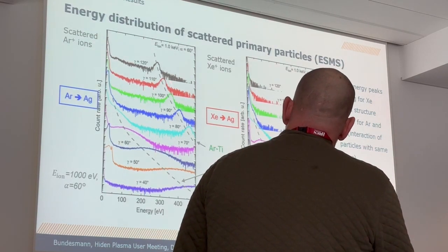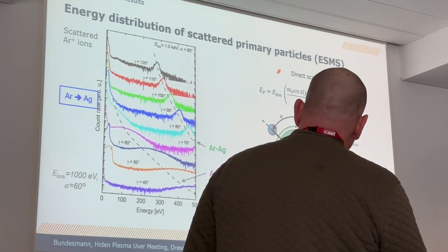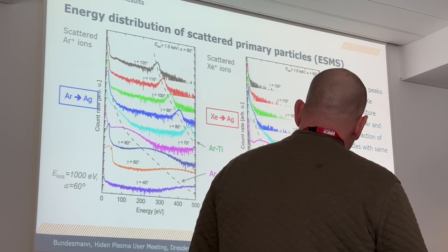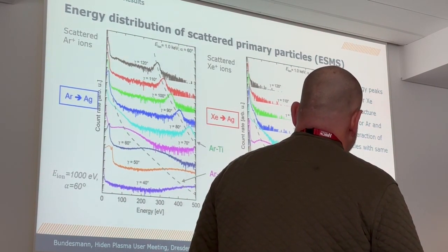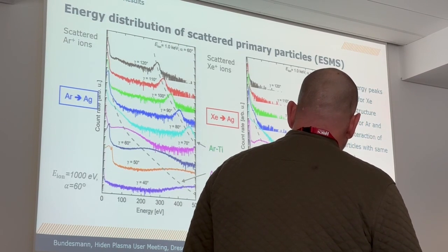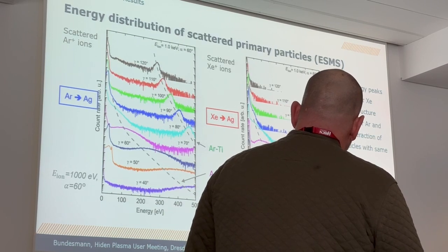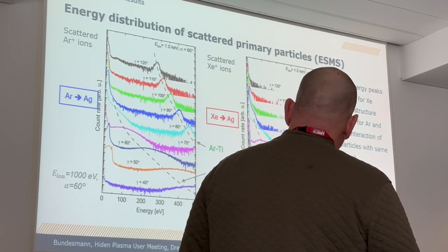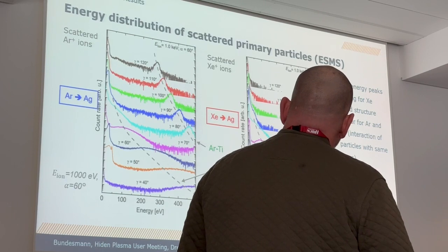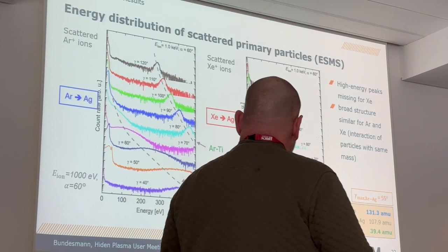So here we have what we already explained. We have a larger scattering angle range than in this case. So this peak is missing. It should appear at an angle of less than 55 degrees. So at 50 degrees, we would expect the peak at about 250 electron volts. At gamma 40 degrees, it would be somewhere around 500. It's not here. Perhaps it's subsumed by this broad structure. I'm not sure, but you see the difference. Keep this in mind. We will need that later on.